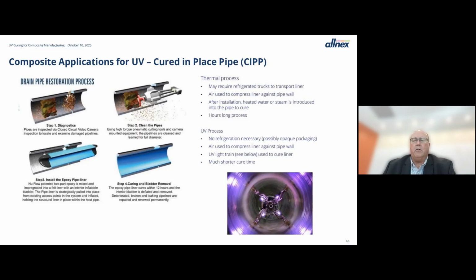Another area that UV has found a home is cured in place pipe. And if you're unfamiliar with the process, instead of digging up pipes to replace them, you can clean the pipes, insert a liner, and then cure that liner either through thermal energy with hot water or steam, or you can cure it with a UV light that passes down through the pipe and cures that liner in place. So it's a very fast process. It means you don't have to dig up lines, and the productivity and fast cure of UV means that you're done with the process in a very short period of time, rather than the thermal process, which could take hours to cure once that liner is in place.